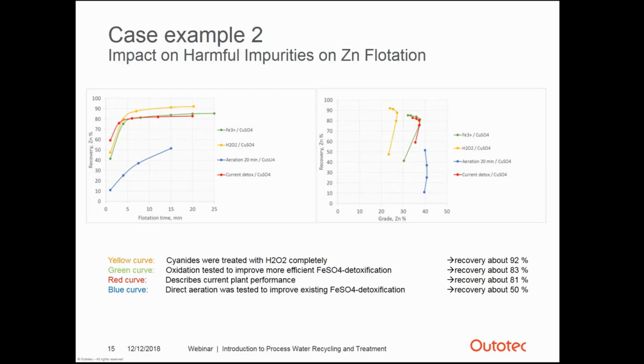It should be noticed that the samples in this study were collected on different days, which means that there are some differences in the head grades, and therefore the tests are not fully comparable to each other. But nevertheless, it can be noted that hydrogen peroxide treatment is the best and most effective method for removing free cyanide from process water. This is according to flotation results. It is likely that the grade of zinc in concentrate could be improved. However, flotation reagent optimization was not included in this test work.